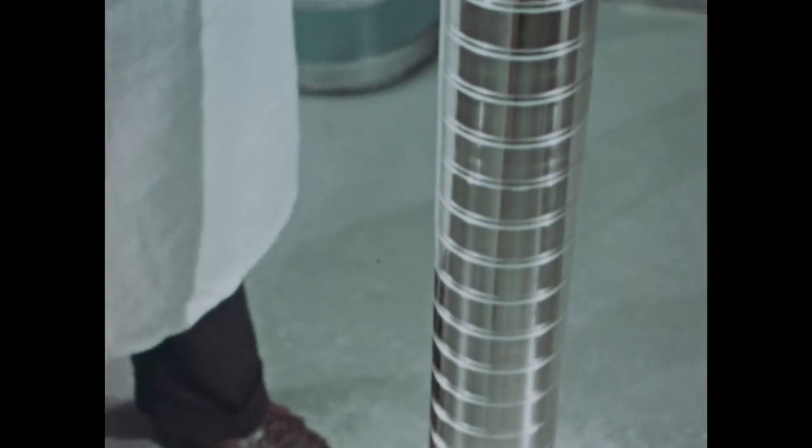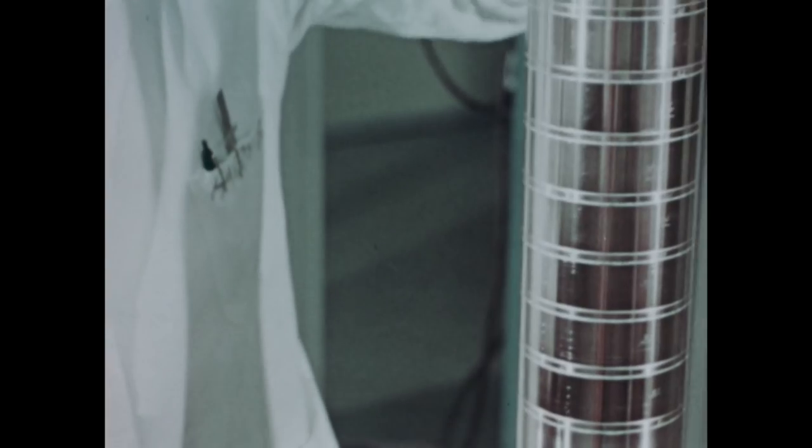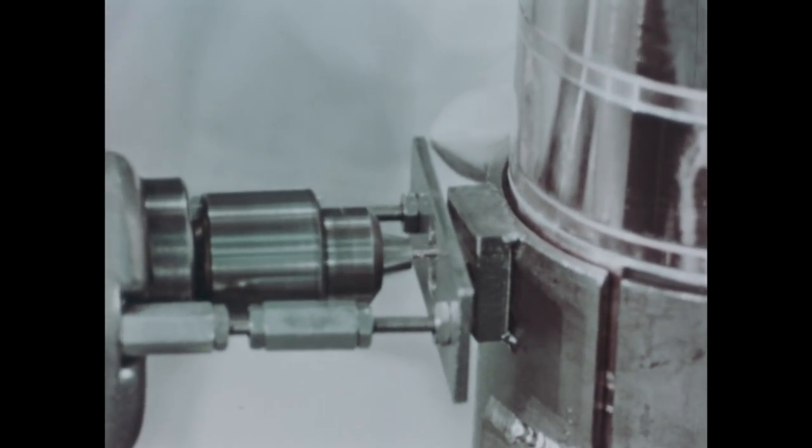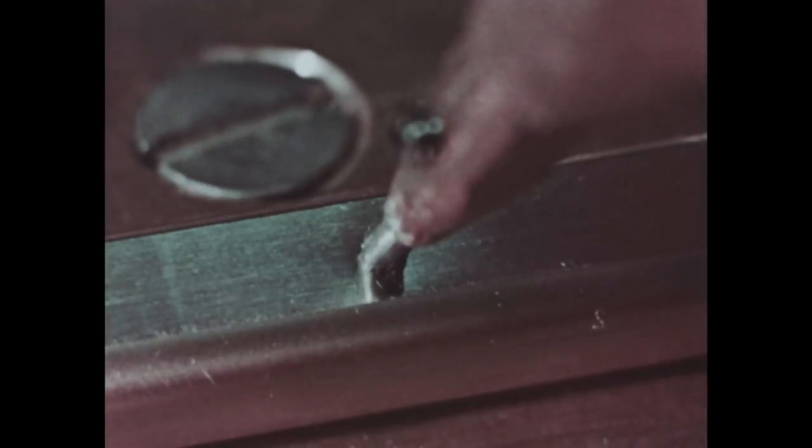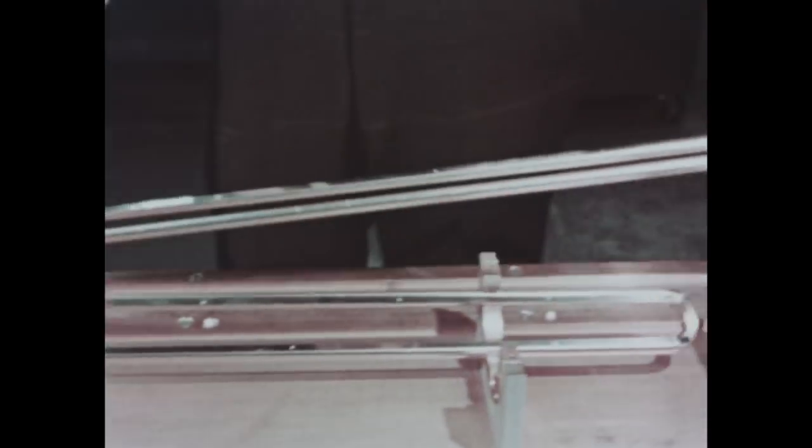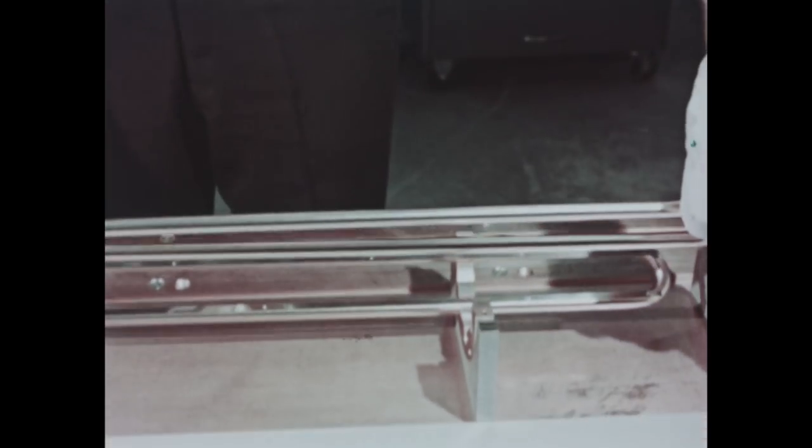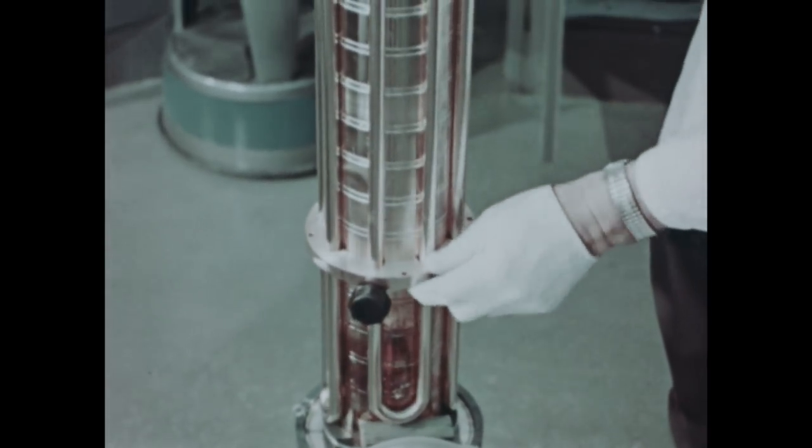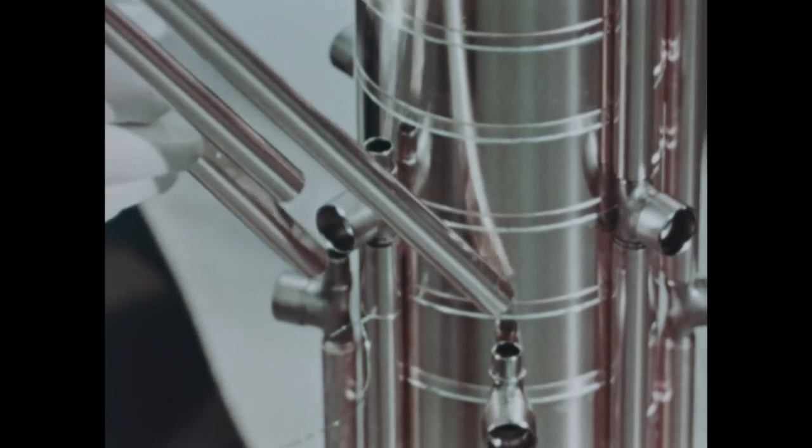The pipe is now transferred to the water jacket assembly area. There has been a time lapse since brazing, so the surface is cleaned with ether. Thermocouple holes are drilled using acetone as a lubricant to keep the section oil-free. Strips of alloy have been previously spot-welded to the cooling tubes. The tubes have been bent into a hairpin shape and clamped together in support rings. Two five-foot sections of tubing are clamped together to form one half of the system.